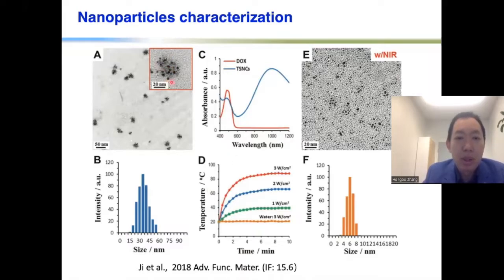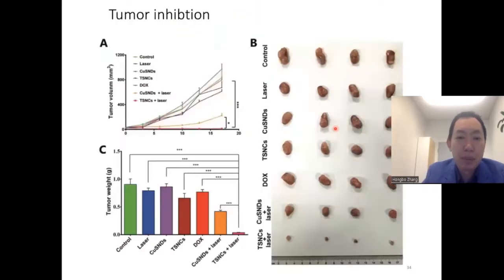So when they reach this tumor site, you can apply a laser, and then this photothermal responsive particle will generate some heat, and then this polymer matrix will degrade. In that case, you will release the smaller particles. And then they are carrying heat, so they are very molecularly active, and they will better drive this drug, doxorubicin, to go deeper inside the tumor. So as you can see, by this method, we can clearly inhibit the tumor in an efficient way.